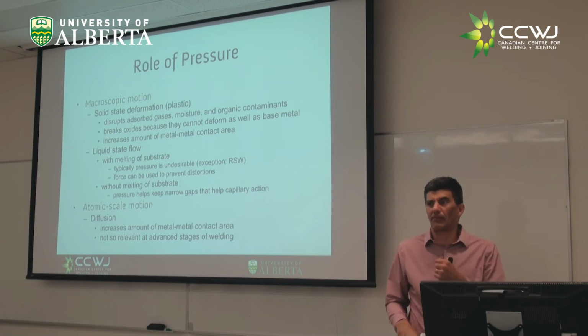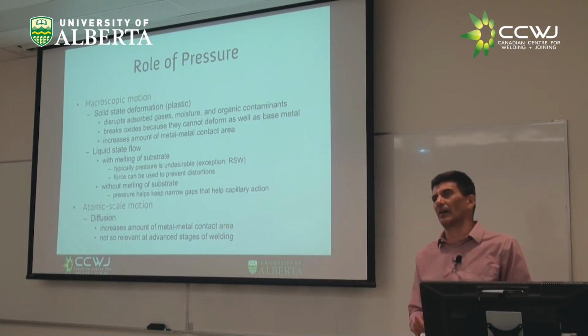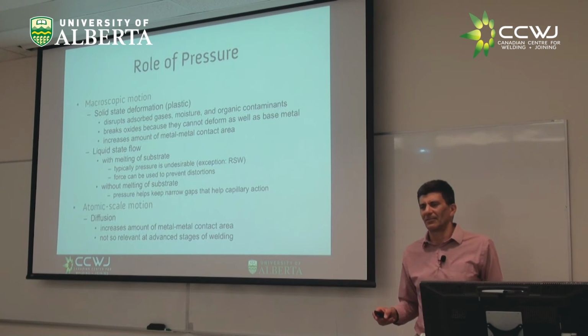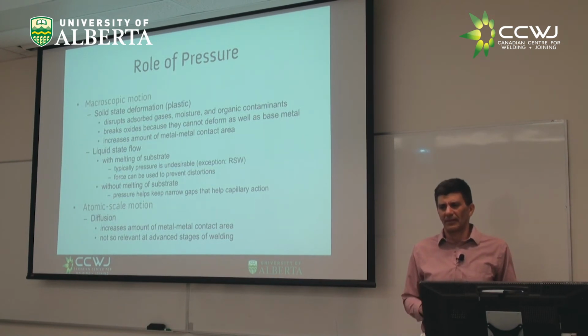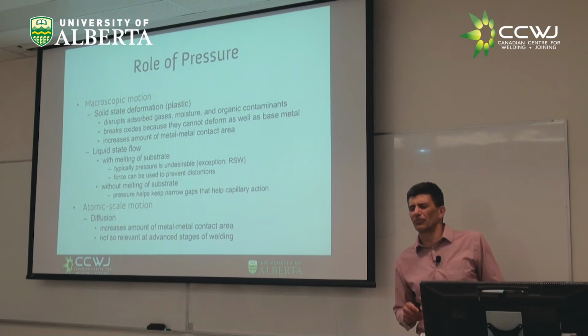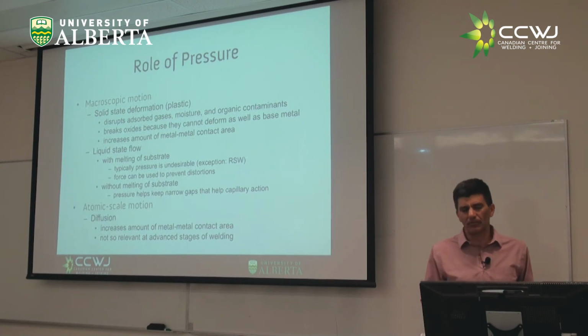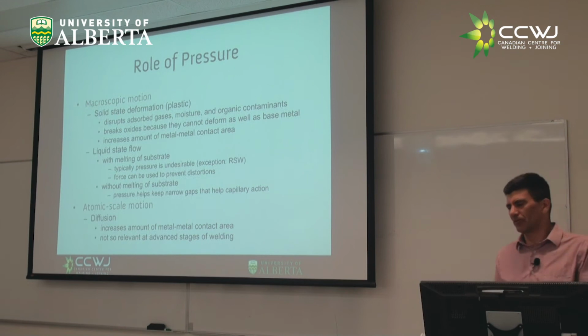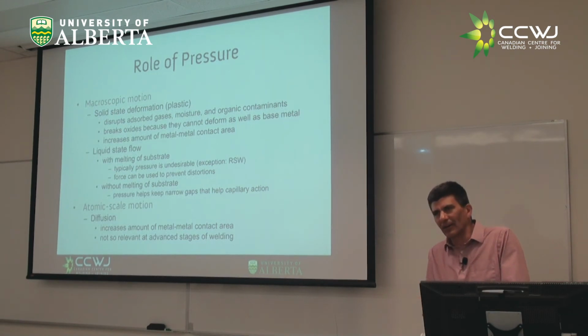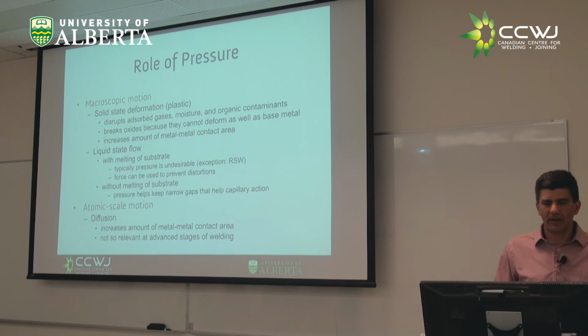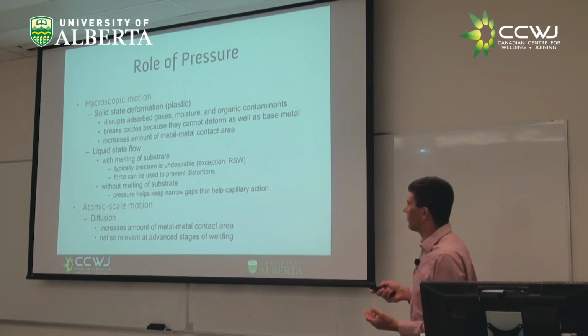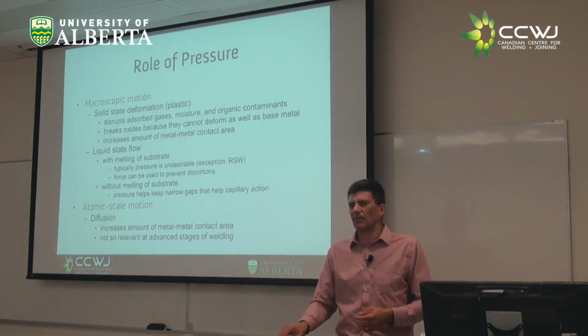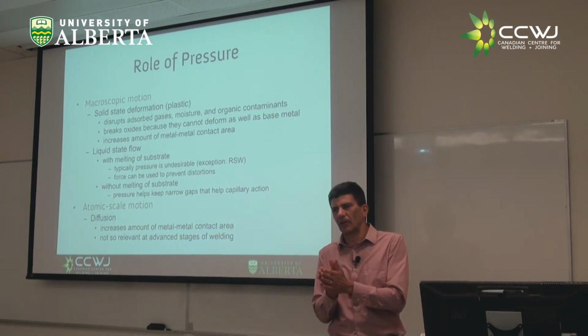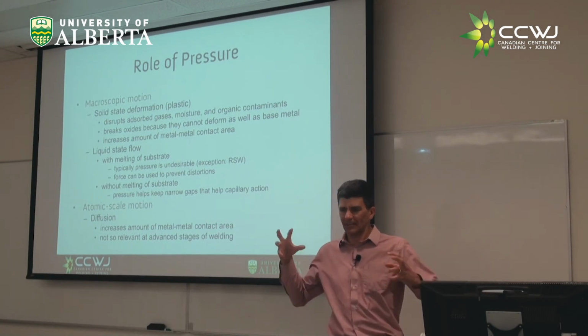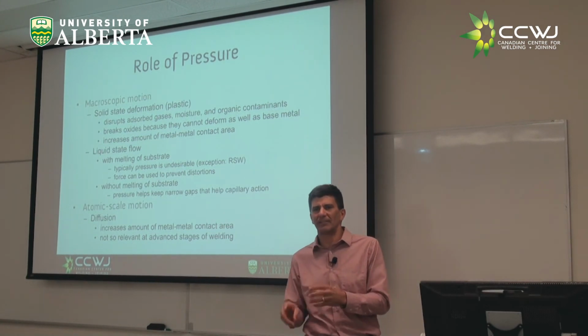But now you know that if you have a plate that is not very flat, brazing is going to suck. It's going to be horrible, very difficult, right? And zero pressure is never too good for brazing, right? Too much pressure might not be good either, right? Because you don't want to start having contact in the asperities. And the atomic scale motion in diffusion, right? Typically, at the beginning, you want to put pressure, so you have these asperities in contact. But the funny thing about diffusion is when it starts to go, you let go of the pressure, and the thing sucks into itself, by itself.